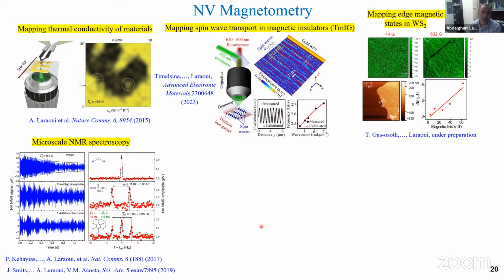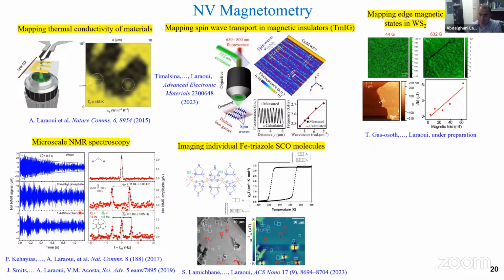NV centers, over the last few years at New Mexico, we use for NMR spectroscopy by using the nuclear spins, whether in the diamond or in this case in water. So you can do very nice spectroscopy. You can even measure J coupling in certain molecules with unprecedented sensitivity and resolution. In my group as well, we use it to study isolated spin crossover molecules. They have a certain memory kind of temperature dependence. Because they are very sensitive, you can measure microtesla fields.